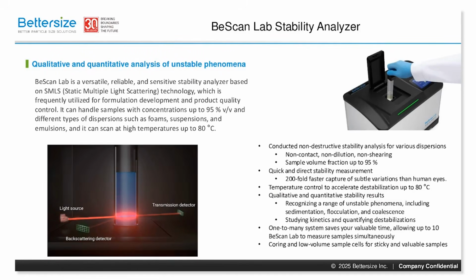To wrap up this section of coating stability, let me introduce the BeScan Lab Stability Analyzer. Based on SMLS technology, the BeScan lab provides quick and direct stability measurements, capturing subtle variations far faster than the human eye. It offers both qualitative and quantitative stability results, recognizing a range of unstable phenomena and allowing you to study destabilization kinetics. This analyzer can handle a wide range of samples, including foams, suspensions, and emulsions, even at high concentration up to 95 percent volume fraction like paints or inks. And because it's non-destructive, non-contact, and requires no diluting or shearing, it preserves sample integrity. With its one-to-many system, you can connect multiple BeScan lab units, saving valuable time by measuring multiple samples simultaneously.